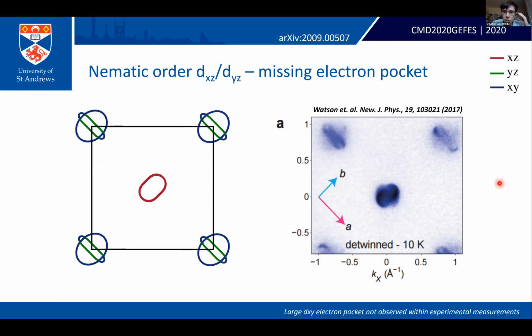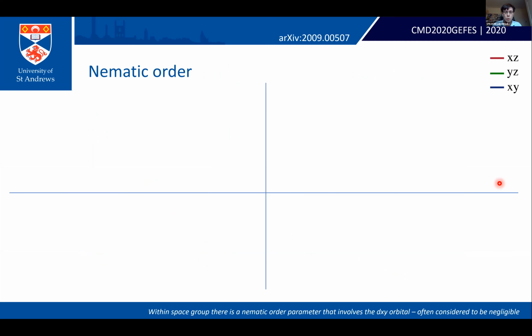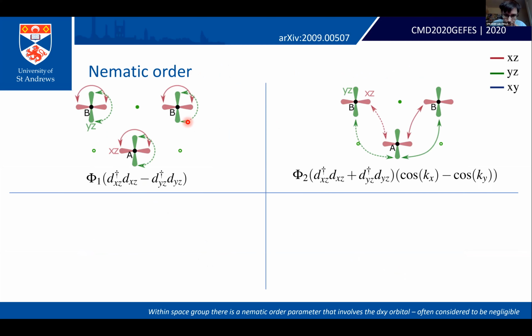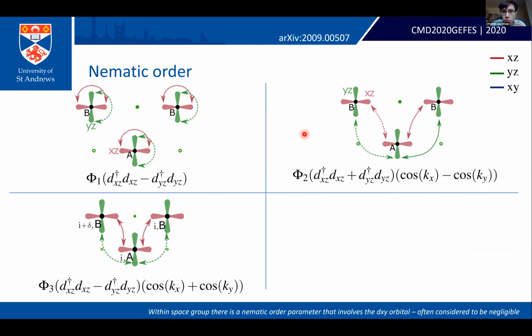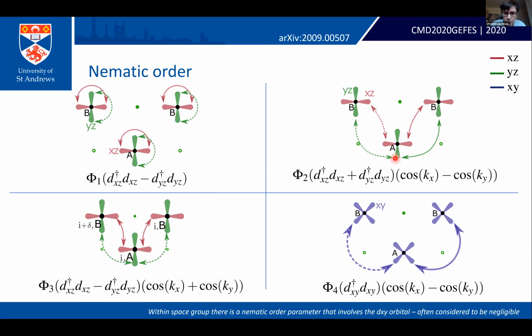So what we did, we went back and looked at the crystal structure of iron selenide, and we thought about all the possible order parameters that you can write down which break the rotational symmetry of the lattice, specifically the B1g rotational symmetry of the lattice, within a single unit cell involving the XZ, YZ, and XY orbitals. And it turns out there are only 4 terms you can write down. The first 3 involve the XZ and YZ orbitals, as I showed on the previous slide. This first term here is a local nematic ordering, and these 2 terms here are non-local nematic ordering between nearest neighbor hopping anisotropy. But a 4th term that's equally valid is a nematic ordering of the dxy orbital, specifically a hopping anisotropy of nearest neighbor iron atoms in the x and y direction.